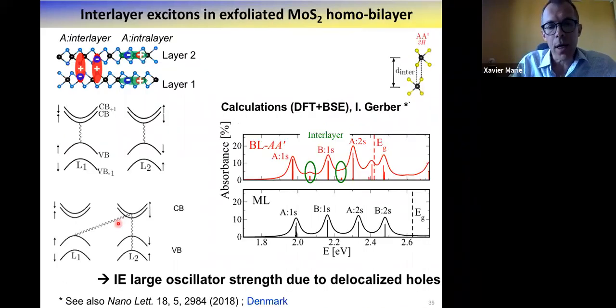So in fact, you have two ingredients to take into account. The first one is the A exciton is this transition, so the bottom of the conduction band and the top of the valence band. The interlayer A exciton, you see, will involve the bottom of the conduction band and the top of the other valence band in the other valley. And then there is this mixing with the intravalley exciton. So the story is a little bit complicated.